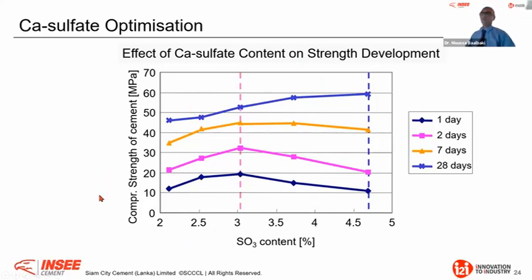And you have, for example, optimization with different SO3 content, different gypsum content, and you see that sometimes you have an optimum for the 1 day, okay? Then when it comes to 28 days, if we, for example, want to achieve high late strengths, probably the optimum will be a trade-off between the early and the late strengths, okay?